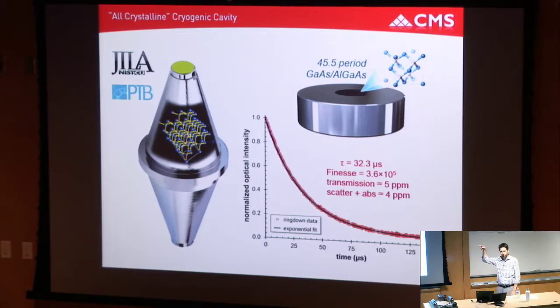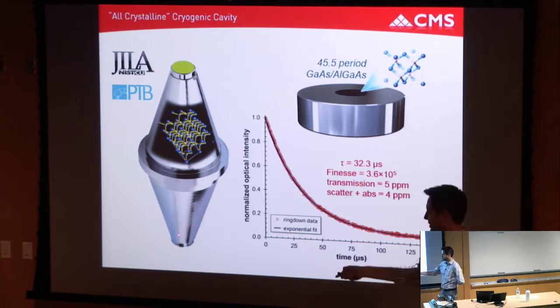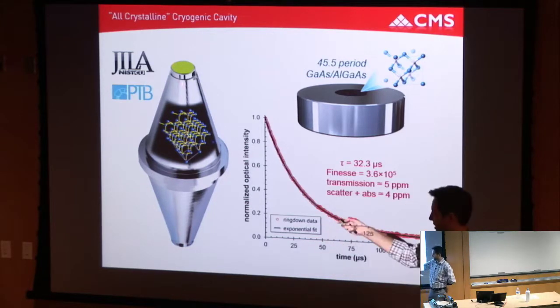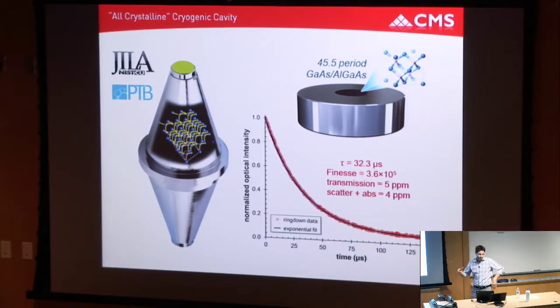So you saw this in the theoretical plot earlier where the coating noise was the main limitation. So now we take our GaAs/AlGaAs coating and transfer it to the surface of that single crystal silicon substrate. This is amazing to me: it is a hunk of single crystal silicon with a central vacuum bore. And then these optics are flipped and contacted onto it. Silicon weirdly crosses zero thermal expansion at 124 Kelvin and at 18 Kelvin. So you can operate at 124 Kelvin with zero thermal expansion in silicon.